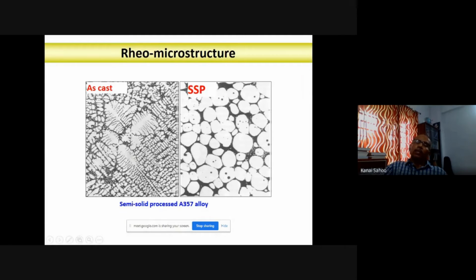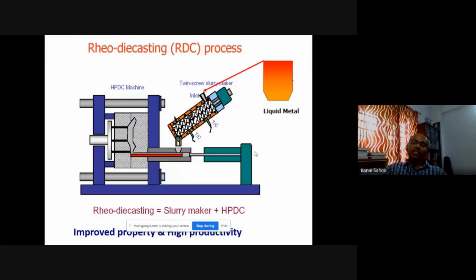Okay, so for this rheocasting there are several parameters you can control based upon your property requirements. But one problem is there. The moment you do the rheocast structure, imagine this is a 357 alloy. This is the as-cast structure, a lot of dendrites, and in the final semi-solid structure, the primary alpha is totally round, totally spherical, and here interdendritic phases are there, which are a little bit elongated; I'll show you the magnified structure. But the problem here is, the moment you start at a solidus-liquidus temperature, as the solid content increases, pouring is very difficult.